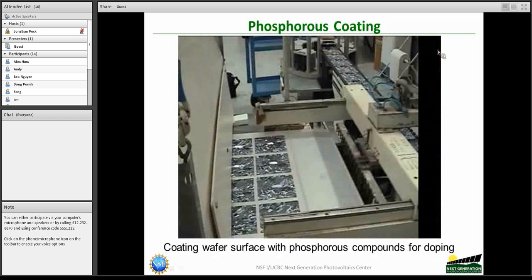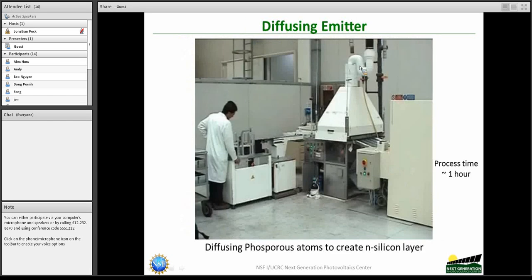The next step involves coating of this phosphor compound on this wafer, and you can see the grains of this polycrystalline wafer material. The phosphor compound is coated to make the N-type dopant. And the next stage is to anneal this coating in this furnace. This step takes about an hour or so to anneal and diffuse the phosphor into the surface of the wafer, converting diffusing phosphor atoms to create an N-silicon layer.